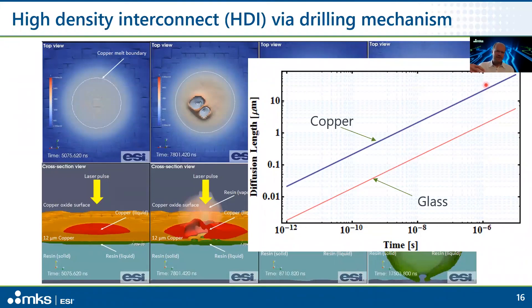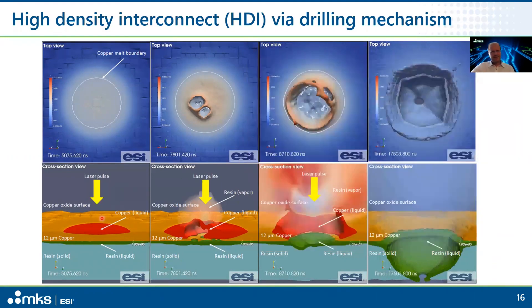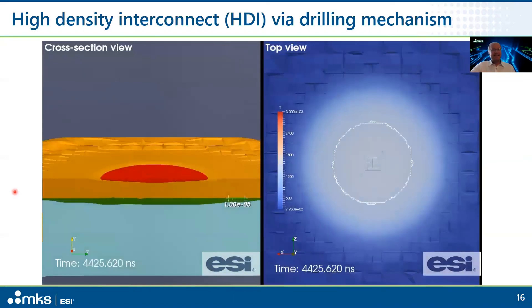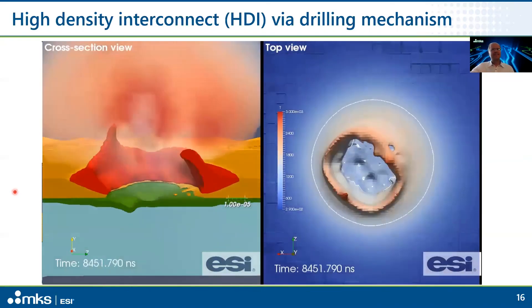If you want to drill the hole in a single pulse, your pulse needs to be on the microsecond timescale. With this long pulse, you melt the copper, heat diffuses down, and the resin starts to boil — its boiling temperature is much lower than the melting temperature of copper. You create a little gas bubble underneath the copper, and as soon as the melt pool breaks through to that bubble, the high-pressure gas pushes through the liquid copper and forms the via.